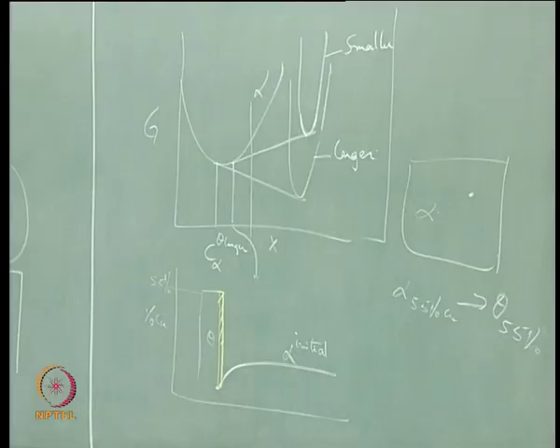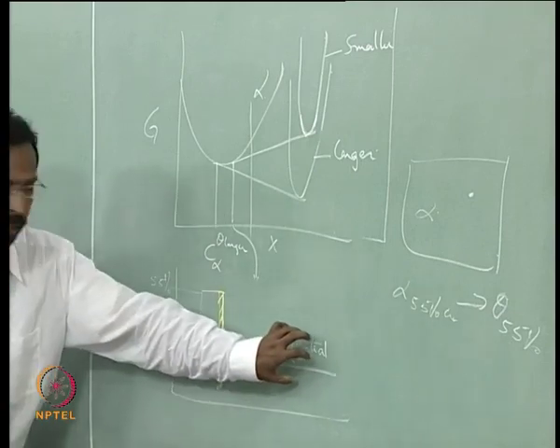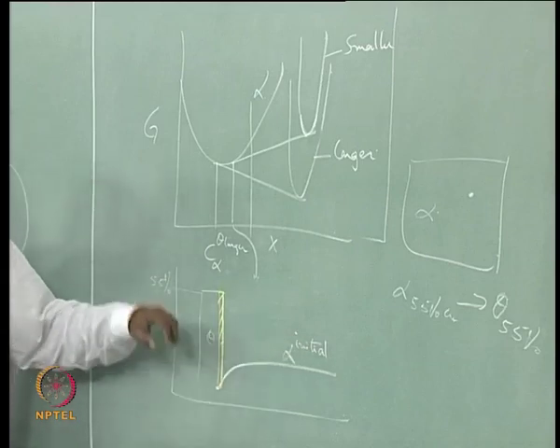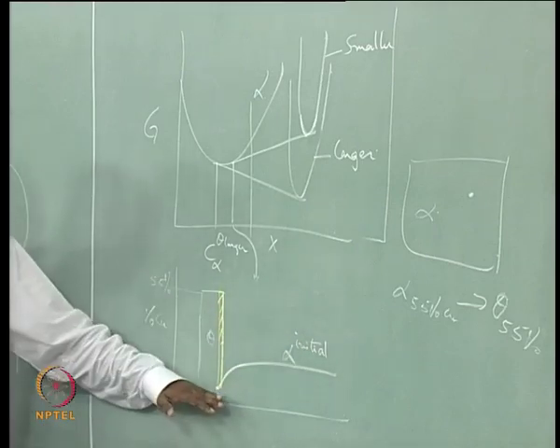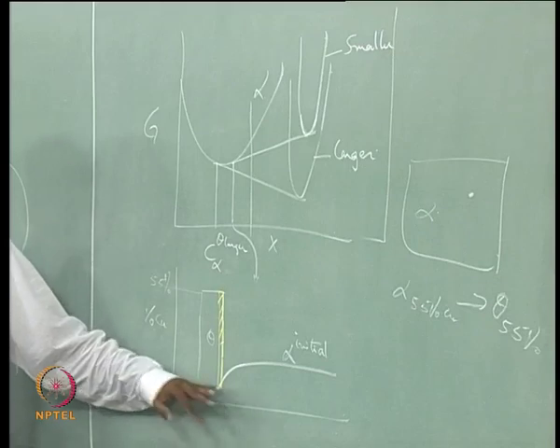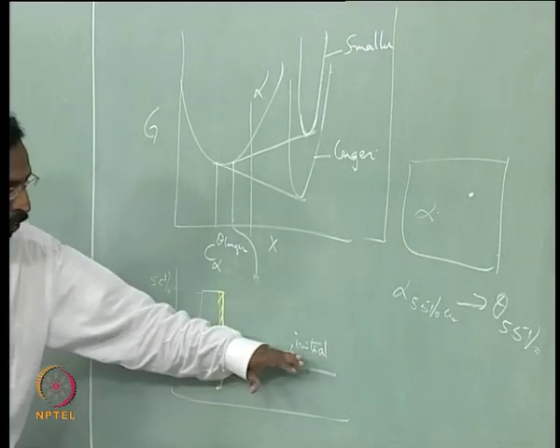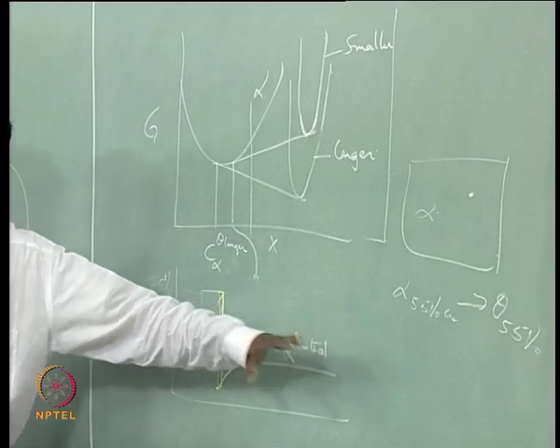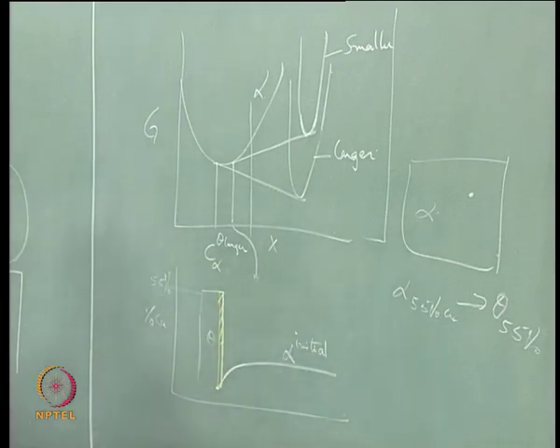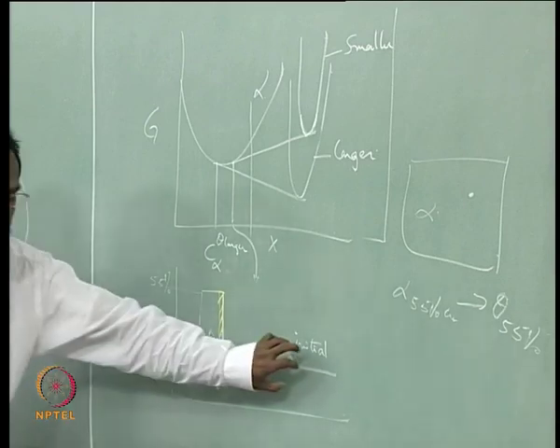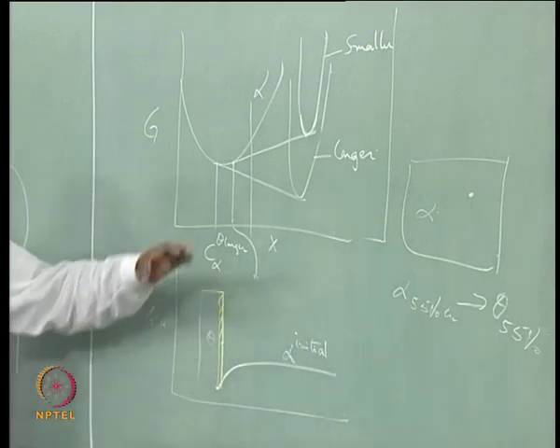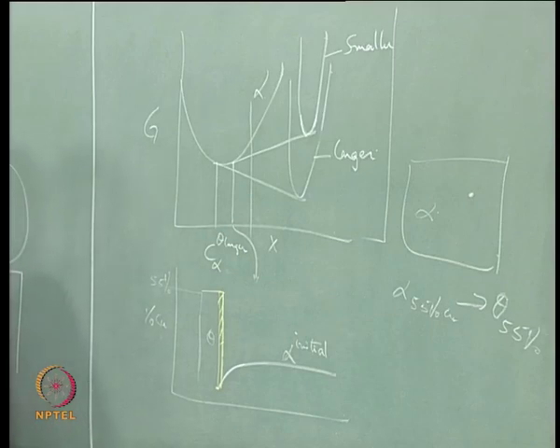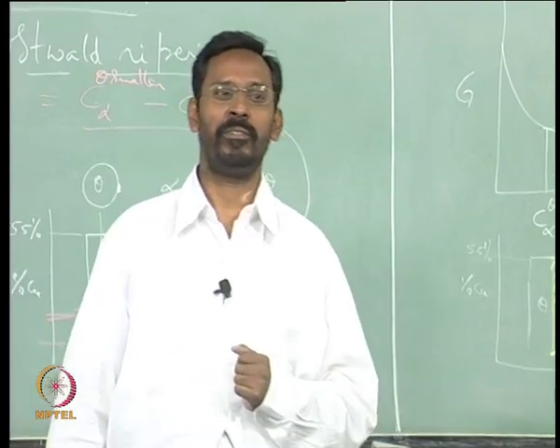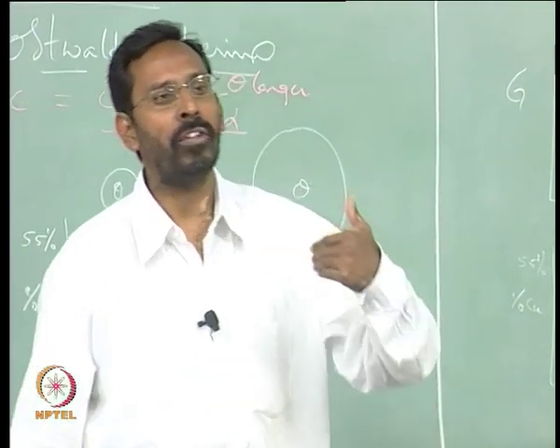Once this value is fixed, what is it that is changing as a function of time in this whole process? You have atoms of copper coming from this region towards this, and then theta is growing, and this is fixed, and then what changes? The composition of alpha in the matrix, what happens to it? It decreases, because the copper atoms are being released from here and coming here. So, the alpha concentration decreases, and once it decreases, what happens to the gradient? The gradient decreases, and as a result the process becomes slower.